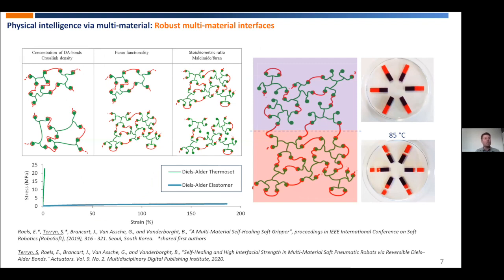So being polymer scientists, we can actually change the composition of the material. So we can change parameters in our polymer networks and then tune the properties, and this can be the mechanical properties. So we can actually make very strong, very hard materials, and we can also make very soft, hyper-elastic materials. Now, but in all of these materials, we have the same reversible crosslinks, which are the Diels-Alder reactions, and therefore we can actually put these two parts together, so two parts which have completely different mechanical properties. We apply a heat-cool cycle, and while everything stays solid, we can actually bind these two surfaces together.